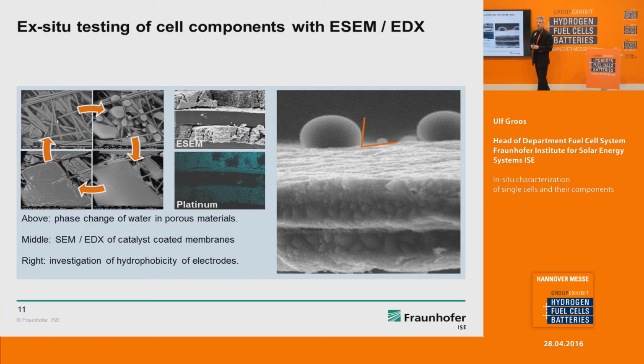At the beginning, I said that we are also doing in-situ testing of different components. So in this case, we look at the CCM within an SEM, a scanning electron microscope. And the speciality of this SEM is that it's an ESEM. It means environmental scanning electron microscope. And this allows us to introduce some water in the atmosphere, so it's not a vacuum. You have some water inside, and by variation of the temperature, you can look at the three phases of the water. So gaseous water, liquid water, and then the water is freezing.